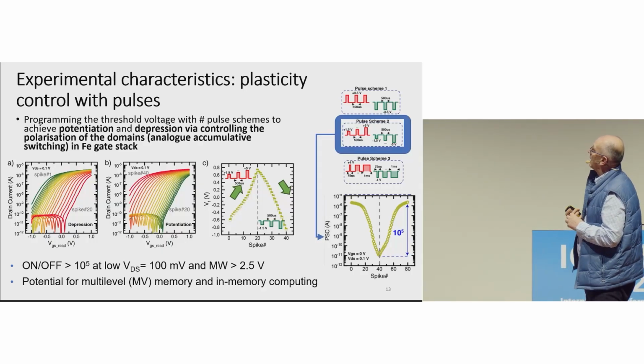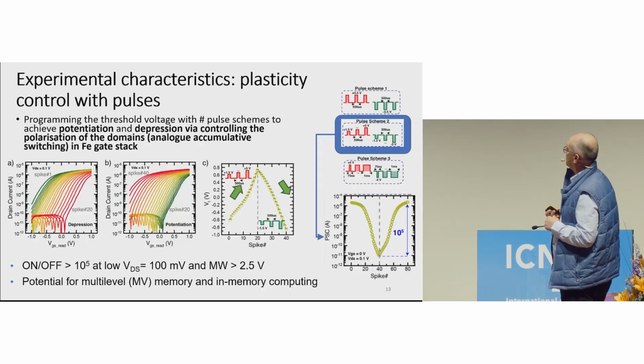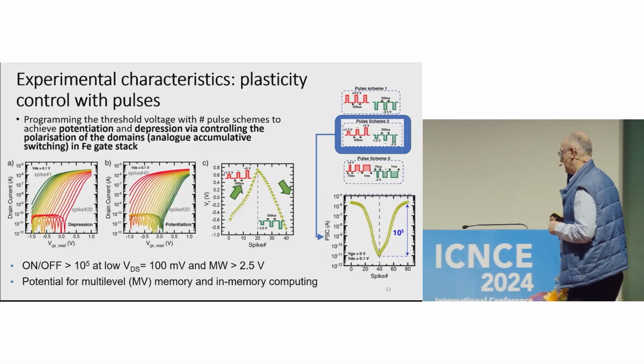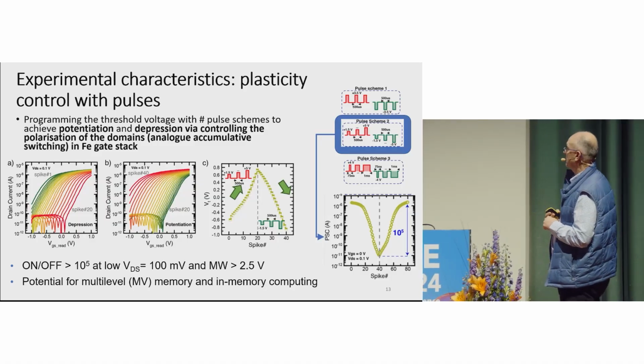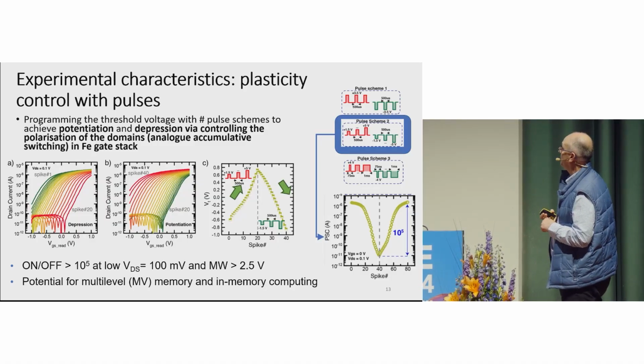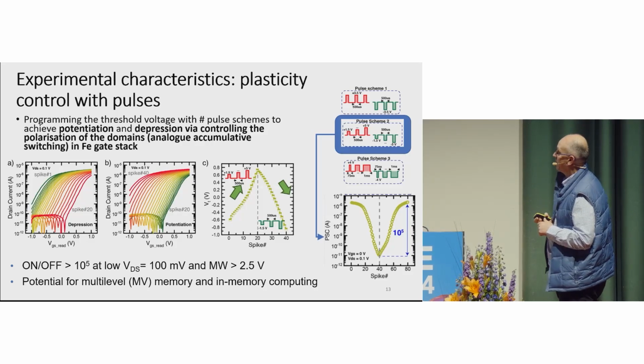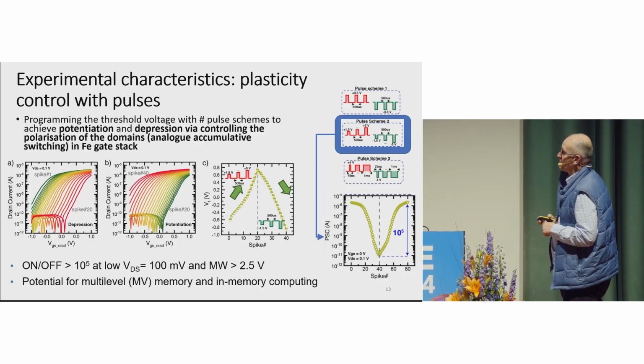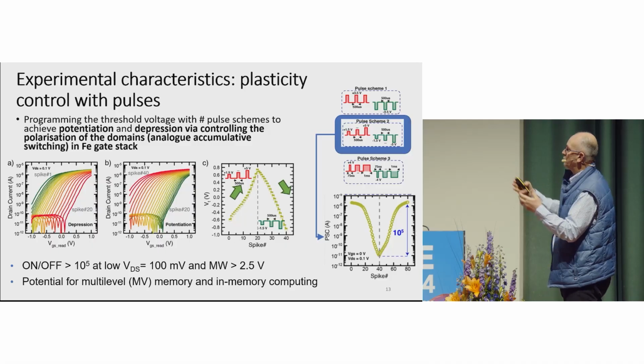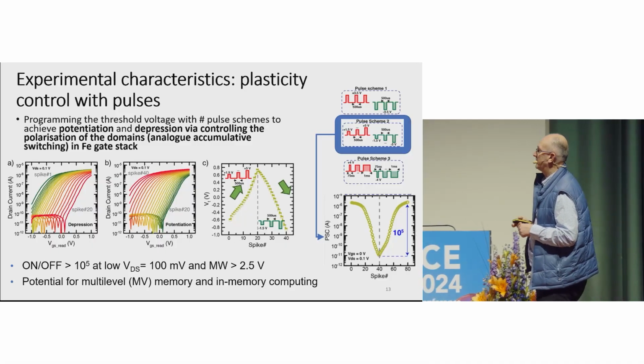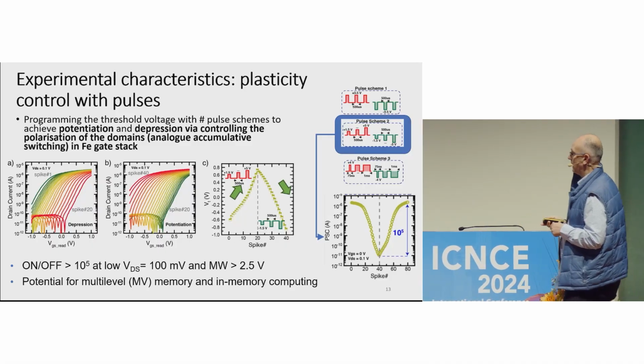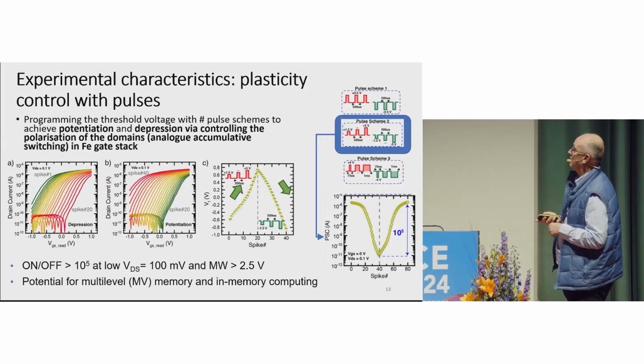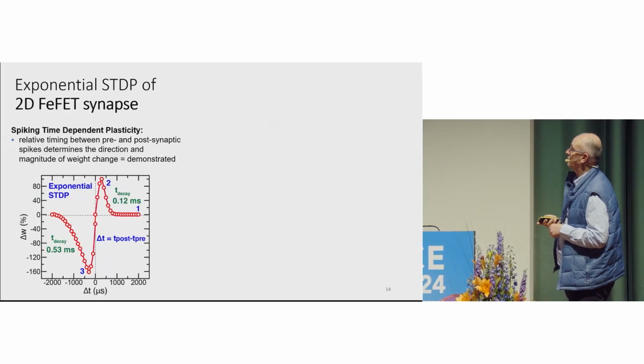and depression curve with an amazing factor. I think this is among the best ever reported in the literature, 10 to 5 in the PSC current. And this, that I can tell you without showing the curve, we have a memory window of around 2.5 volt, and we believe this device has an extremely interesting potential for the future.